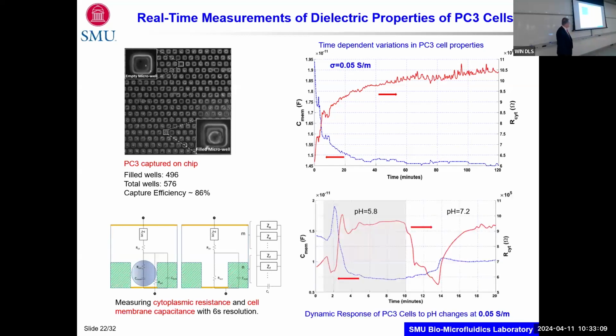But despite that, we were able to alter, for example, pH. And I would expect time periodic variations in these properties. The reason I'm not seeing that is because of these temporal shifts that are happening. So in order to use these kinds of techniques, you have to go to high conductivity and hope that it works. Otherwise, everything is going to be on a transient scale.